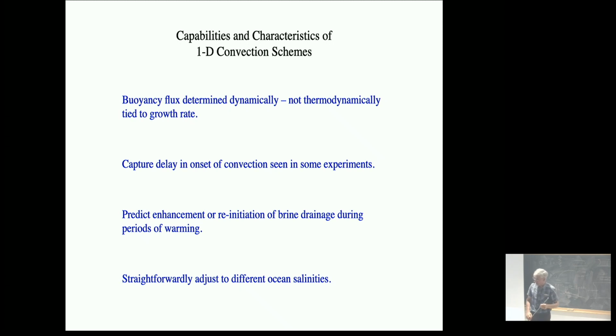It was something that was known as the Baltic Sea problem for a long time. The Baltic Sea is relatively fresh in its surface layers, and the climate models before this sort of modeling predicted that salt was sucked up from the ocean into the sea ice in the Baltic regions. And that's because it assumed that the sea ice has a certain fixed salinity, okay, which was greater than the salinity of the Baltic Ocean. So, you know, you can take fresh water and freeze it and form salty sea ice. You can't.